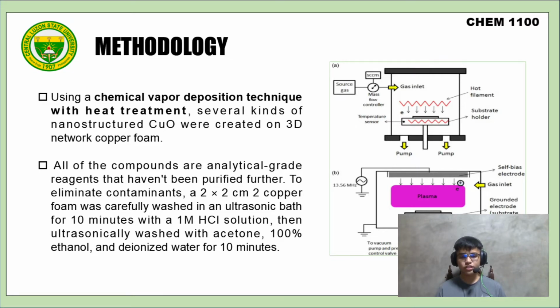So for the methodology, using a chemical vapor deposition technique with heat treatment, several kinds of nanostructured copper oxide were created on 3D network copper foam. All of the compounds are analytical grade reagents that haven't been purified further. To eliminate contaminants, a 2 by 2 cm² copper foam was carefully washed in an ultrasonic bath for 10 minutes with 1 molar hydrochloric acid solution, then ultrasonically washed with acetone, 100% ethanol, and deionized water for 10 minutes each.